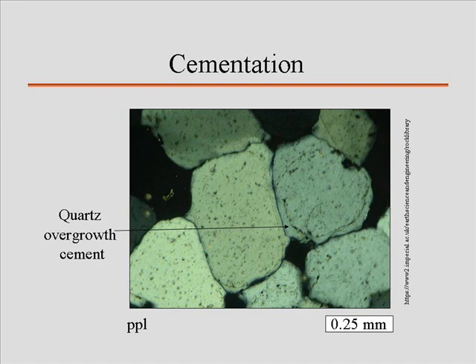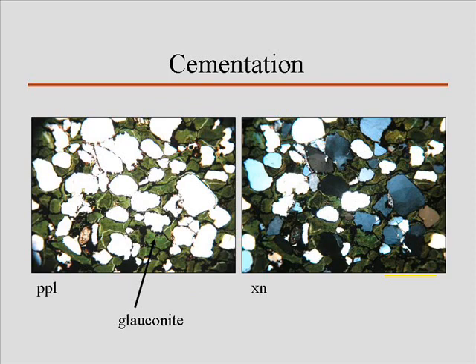Here's another grain. Actually, this one's hard to actually see the grain. Here you can see the edge of the grain quite nicely. It's a different orientation. There's the cement, there's the grain, but notice even though it's a different orientation, optical continuity, optical continuity. That is characteristic of quartz overgrowth cements. Some of you saw this very thin section in your first thin section lab in this course. This is the glauconite cement.